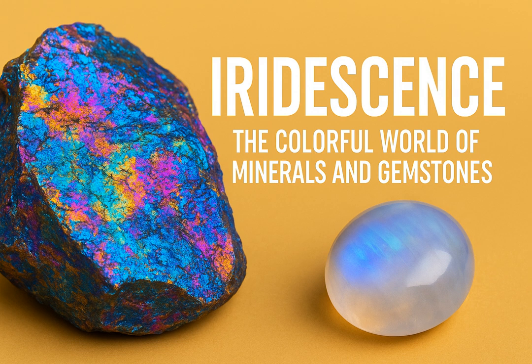Got it. So what's the deeper science behind Bornite's spectacular dynamic sheen beyond just the surface tarnish creating those oxide films? Right, because there's more to it. It's intrinsically linked to its internal structure and how that structure actually changes with temperature. Oh, interesting. How so? At temperatures above 228 degrees Celsius, that's 442 Fahrenheit, Bornite actually has an isometric, or cubic, structure internally. Okay, so hot Bornite is cubic. Essentially, yes. At that temperature, its atomic framework is based on cubic, close-packed sulfur atoms, with the copper and iron atoms just randomly distributed within those spaces. It's a bit disordered.